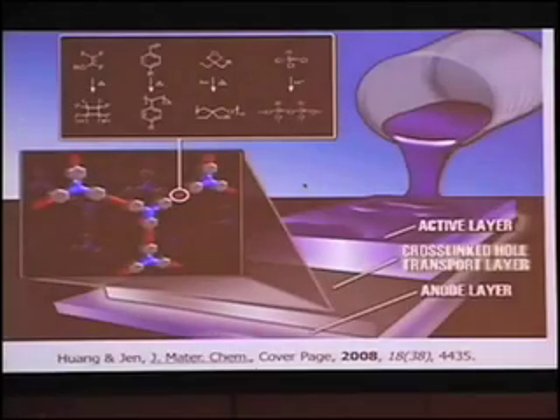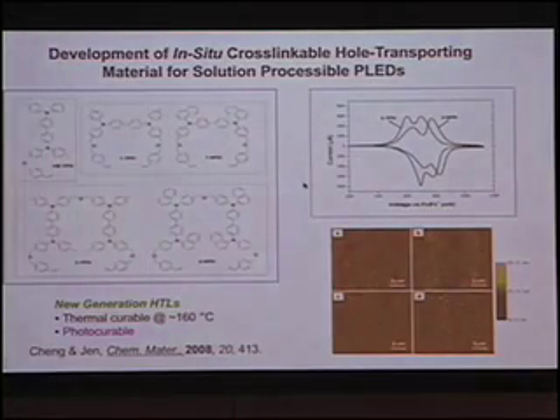So this is one slide to summarize some of the work. We can basically take any of the so-called hole transporting molecules and utilize different kinds of functionality. You spin this small molecule, then you heat it up in situ. You shine a light or heat it up. They form a very nice cross-linked network. As a result, you have very robust mechanical properties. So you have some hole transporting molecule, and when you spin that, it forms a very smooth film and a very electrochemically active material.